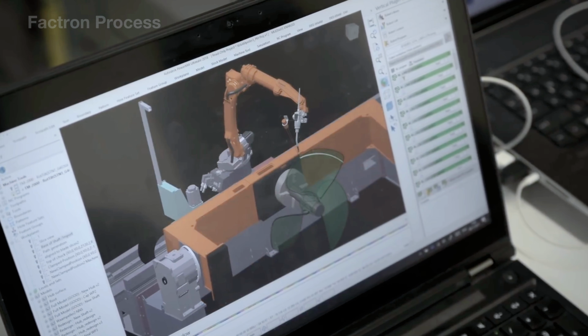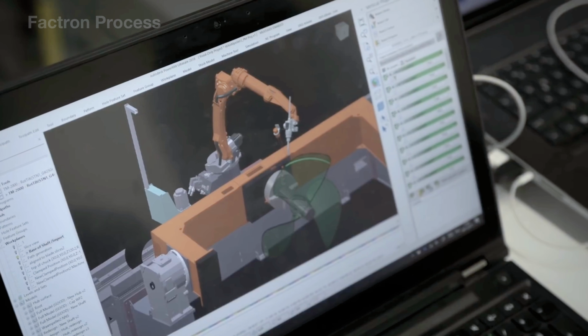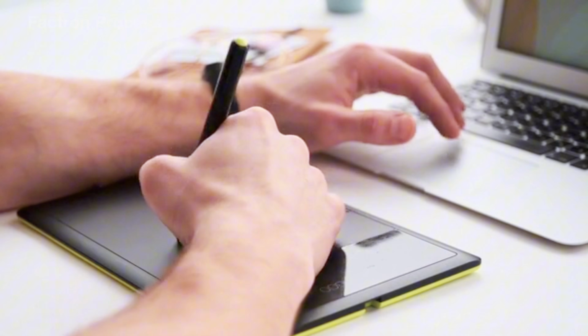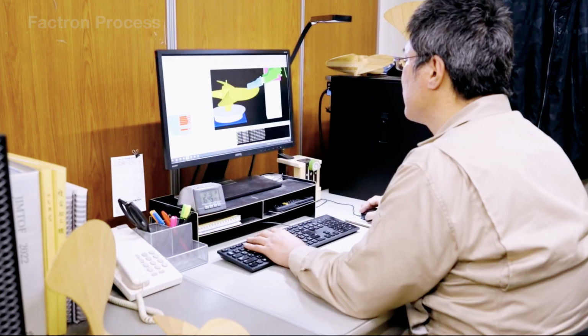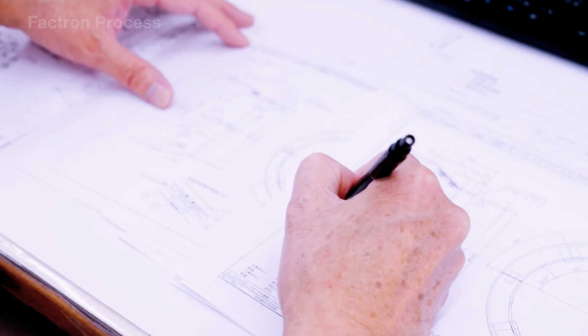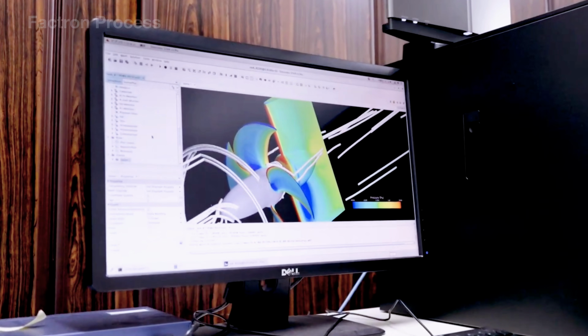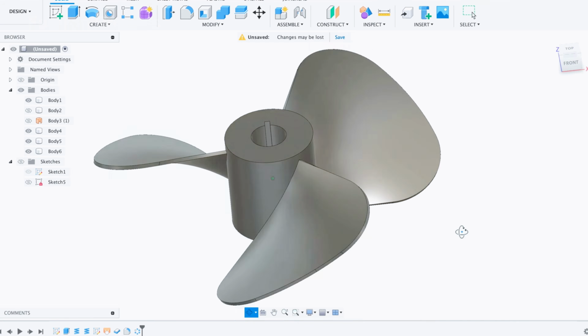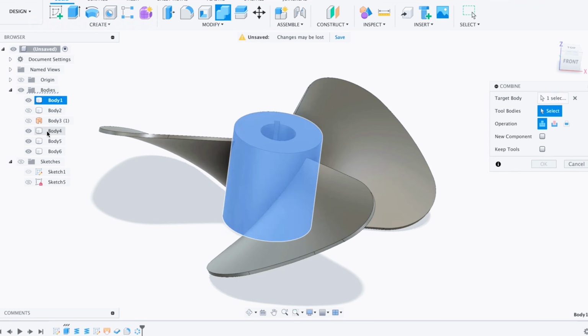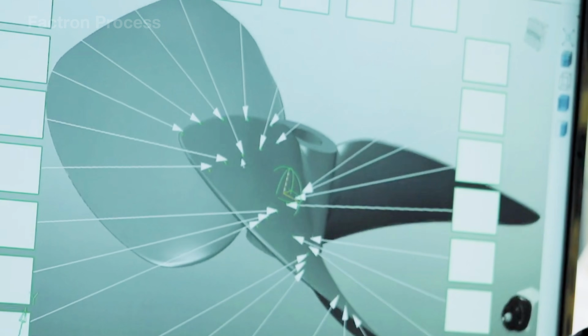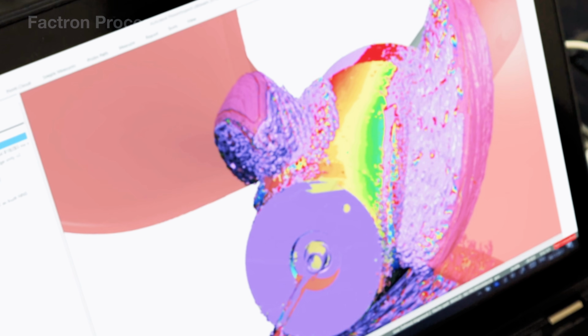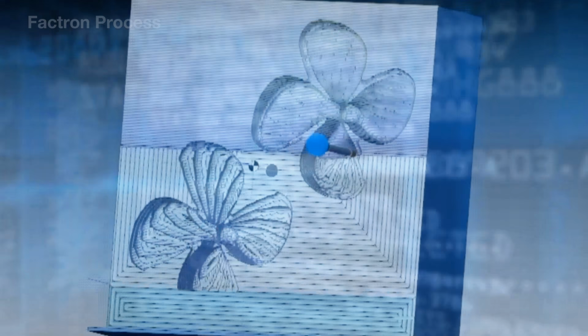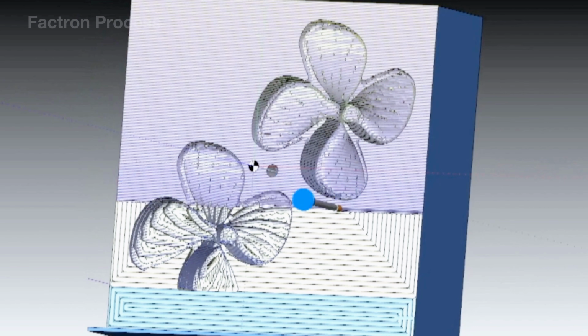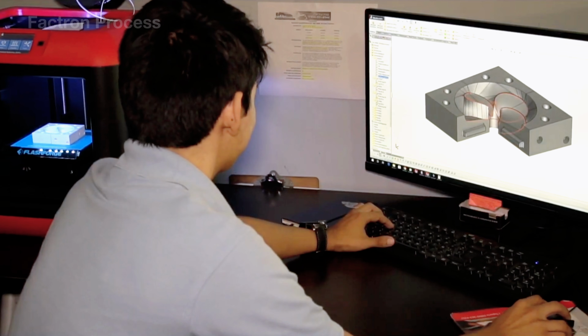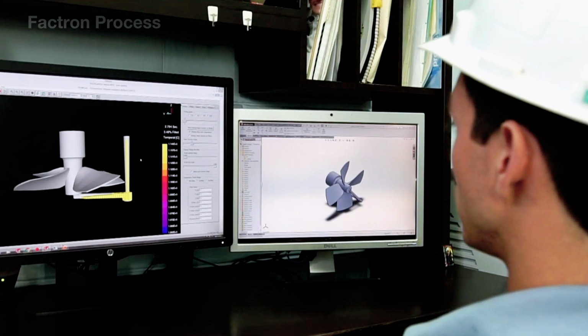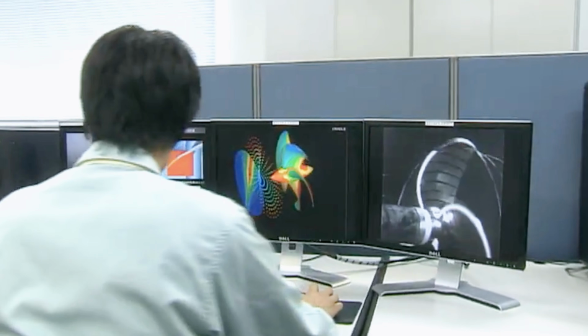From this data, software creates a 3D propeller model and simulates water flowing across each blade. On the screen, the water current passing over every blade reveals regions where energy is lost or pressure suddenly drops. Cavitation appears at these points. The pressure falls so sharply that water boils even at normal temperatures, forming bubbles that continuously eat away at the propeller surface over time. Therefore, every twist, angle, and curve is rigorously examined in the simulation. A small adjustment becomes a difficult decision, aimed at optimizing efficiency and reducing hundreds of thousands of dollars in annual fuel costs.